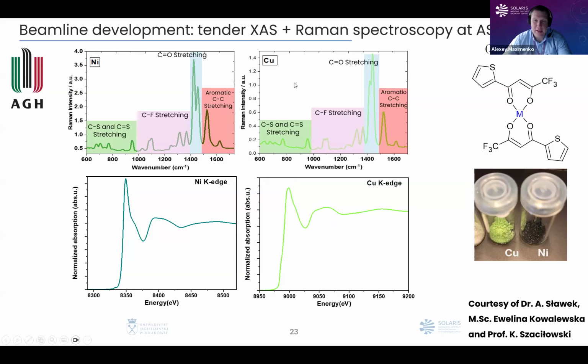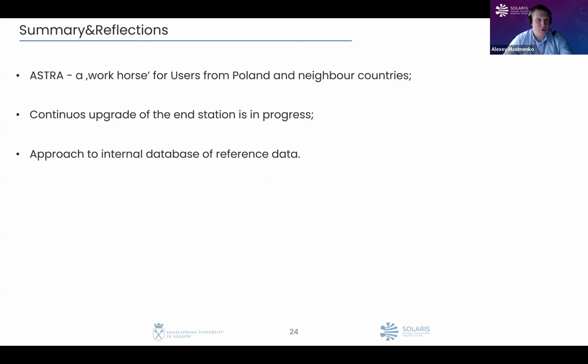And what is also very important, sometimes when you prepare your publication, the reviewers ask how you could prove that what you are measuring at the synchrotron is the same sample which you measure in your laboratory. So in order to help our users to overcome such a question from the reviewers, when you come to our beamline, we could measure your sample and you can then compare Raman spectra which you can measure at your university, and then you can tell every reviewer that this is the same sample which was measured in my laboratory. So, in the end, as my conclusion, I would say that ASTRA is quite a compact beamline.